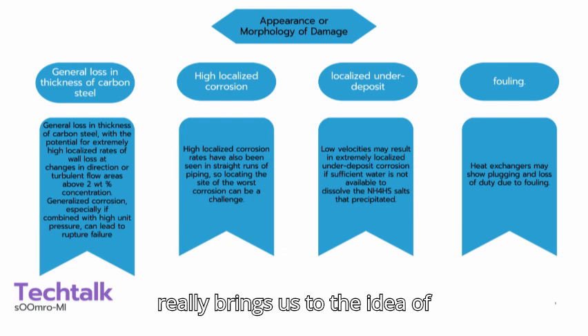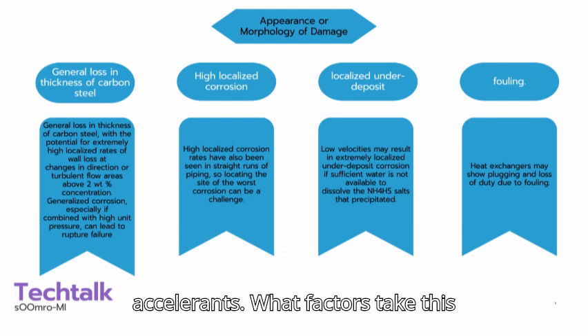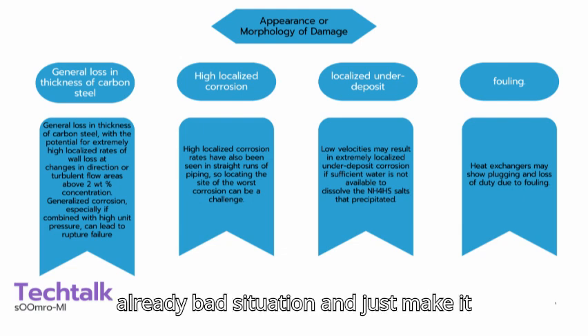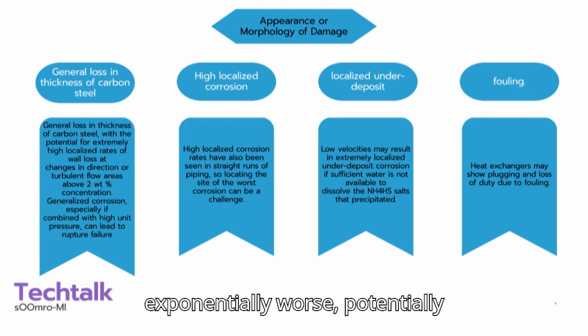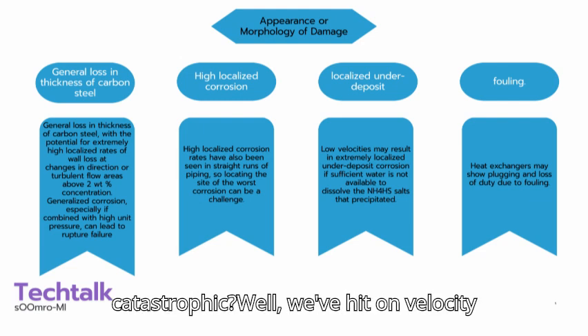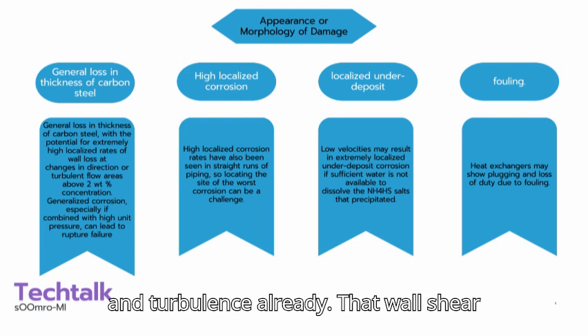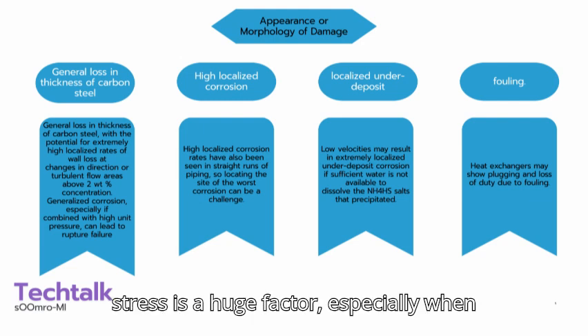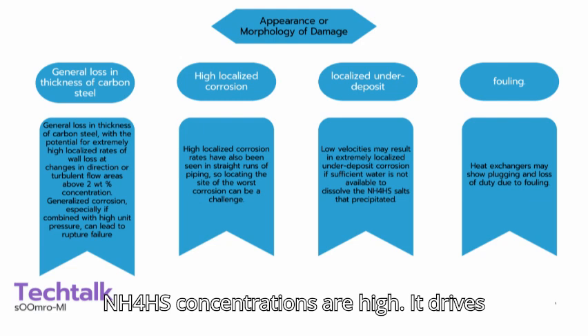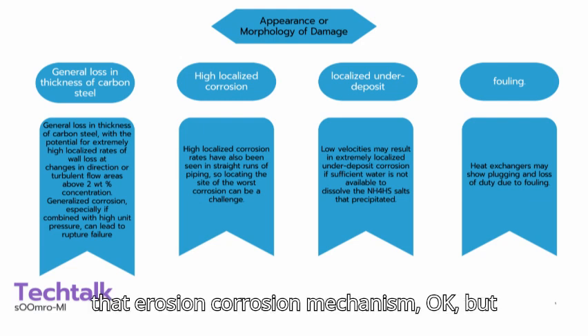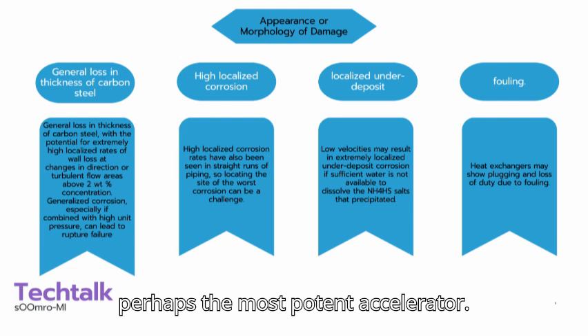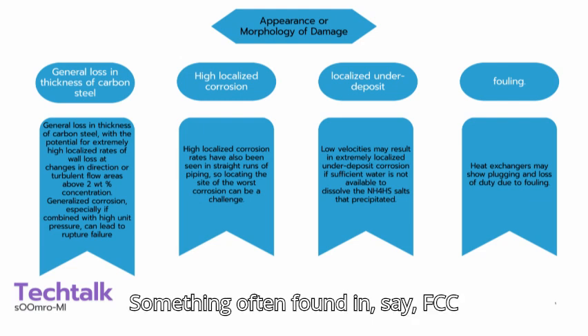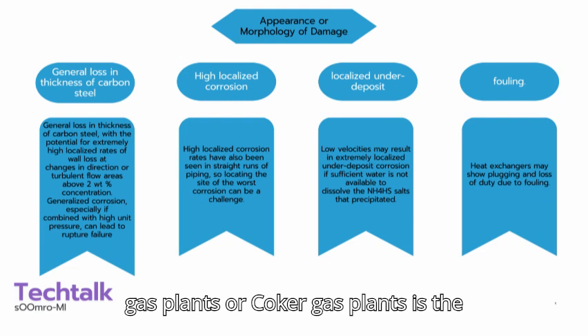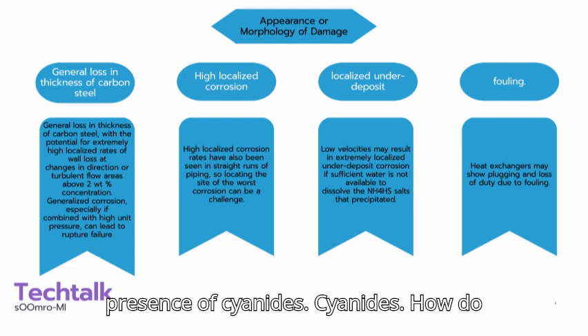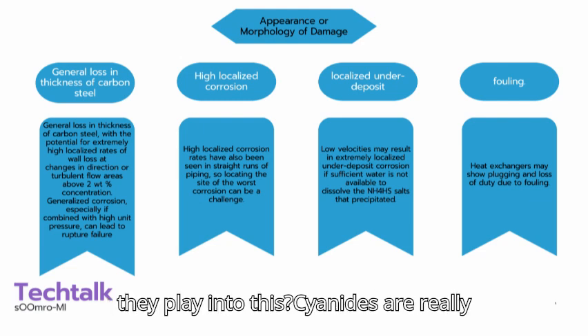It really brings us to the idea of accelerants. What factors take this already bad situation and just make it exponentially worse, potentially catastrophic? Well, we've hit on velocity and turbulence already. That wall shear stress is a huge factor, especially when NH4HS concentrations are high. It drives that erosion-corrosion mechanism. But perhaps the most potent accelerator, something often found in, say, FCC gas plants or coker gas plants, is the presence of cyanides. Cyanides. How do they play into this?